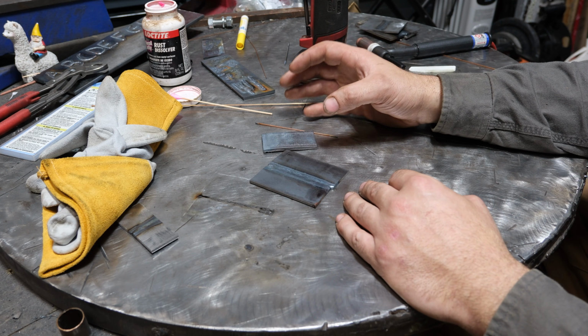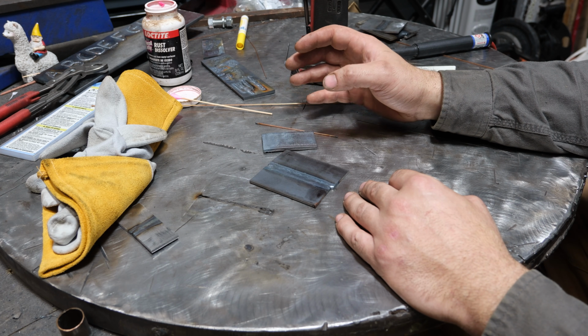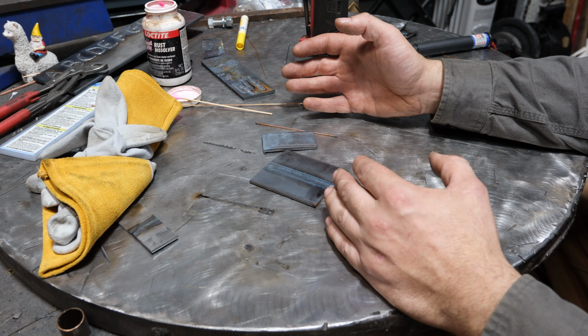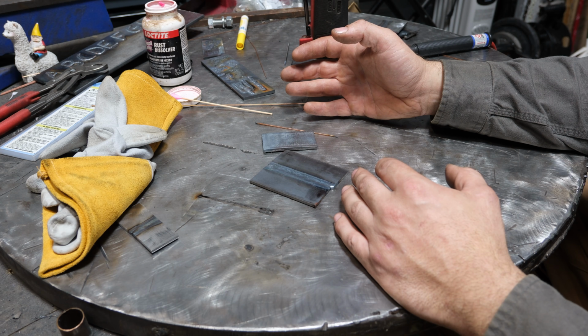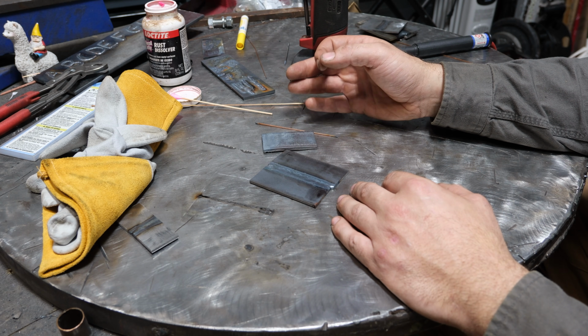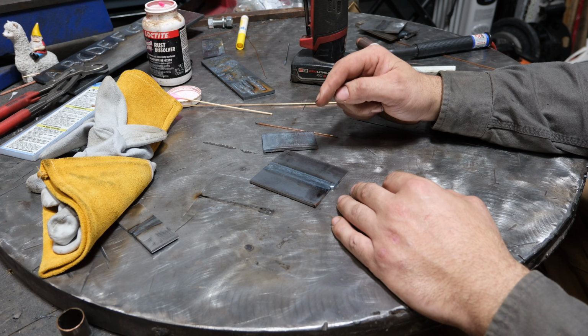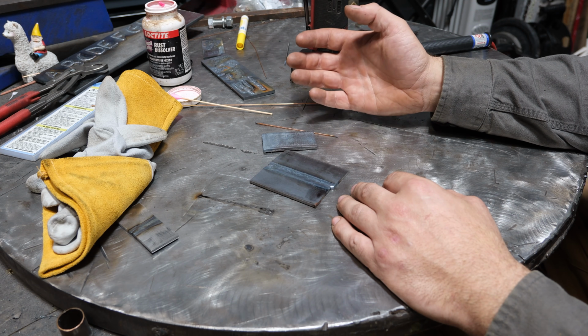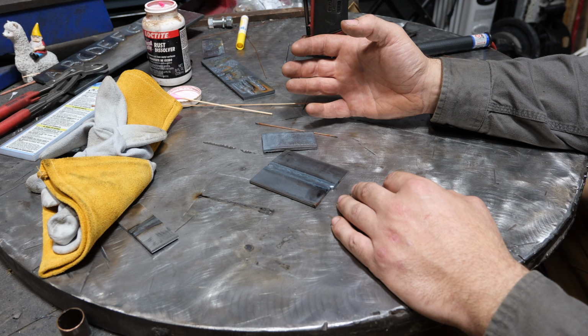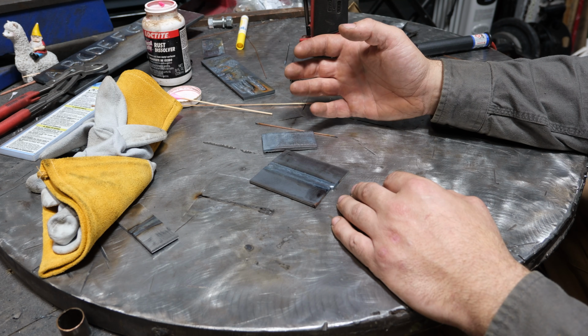The same things that affect MIG and stick also affect TIG. Like, people like doing stacks of dimes with MIG. Well, if you try and make a perfect, nice, clean looking stack of dimes with TIG, odds are you're running too cold. And because of that, you're going to have no fusion and you're making weak welds.